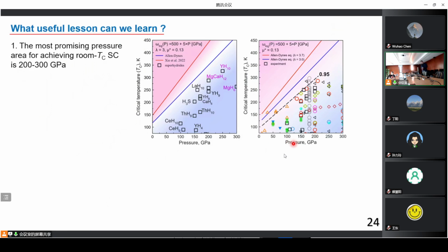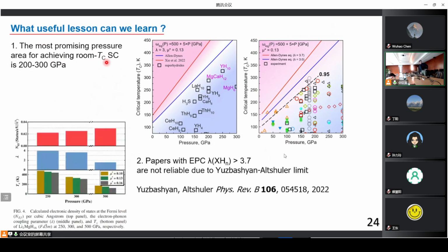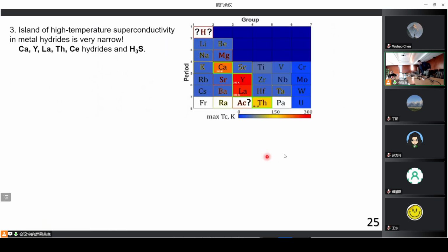Okay, that's all. I just would like to remind and make several conclusions. The most important points of my presentation: the most promising pressure region, as I told before, for achieving room temperature superconductivity is probably between 200 and 300 GPa, a little bit higher than people usually use. We should not trust a lot the papers which violate the Yuzbashyan-Altshuler limit for conventional electron-phonon interaction described within Migdal-Eliashberg theory. The limit is 3.7, and if we see a paper with 4, it means they're probably not reliable.